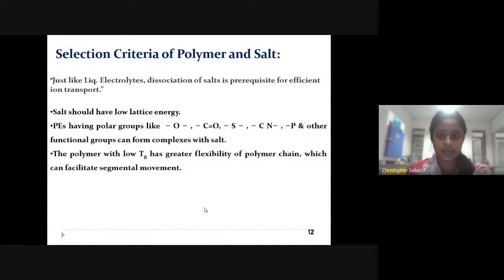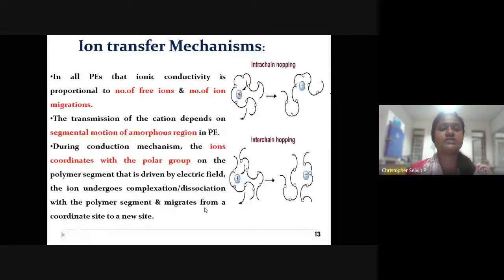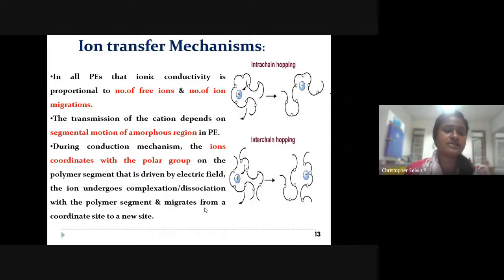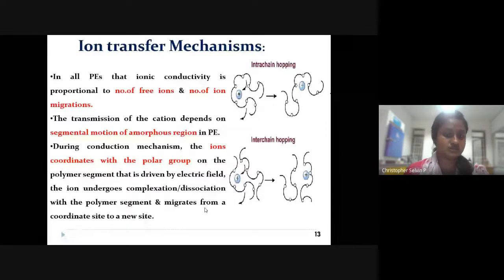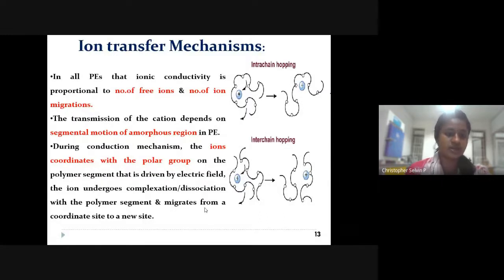Ion transfer mechanisms. These are the possible mechanisms that can take place inside a polymer chain. One is intra-chain, and the other one is interchain hopping. So in all polymer electrolytes, the ionic conductivity is related to the number of free ions and the number of ion migrations. The transmission of cation depends on segmental motion of the amorphous region in the polymer electrolyte. And during the conduction mechanism, the ions coordinate with the polymer and are driven by the electric field. The ion undergoes dissociation with the polymer segment and migrates from a coordinate site to a new site.